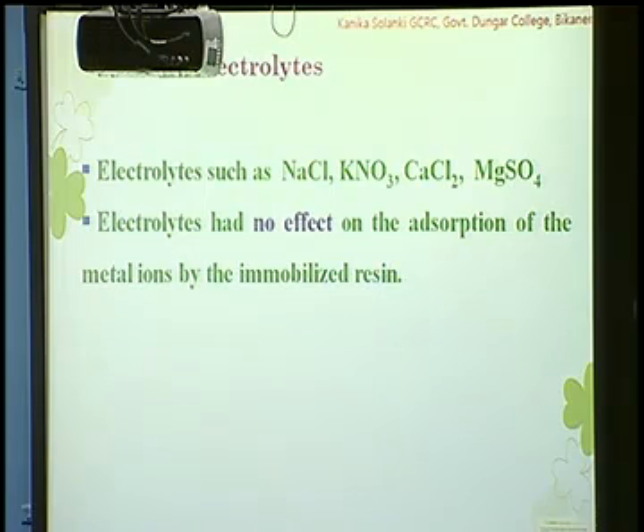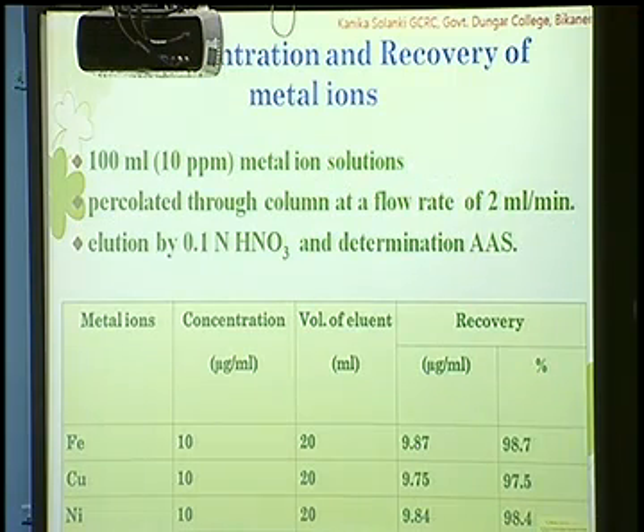marginally. The effect of flow rate was also investigated by the column method. The most suitable flow rate found is 2 ml per minute. The effect of electrolyte had no effect on the adsorption of metal ions by the immobilized resin. The pre-concentration and recovery of metals, as you can see, we were able to recover 98.7% of Fe, 97.5% of copper, and 98.4% of nickel.